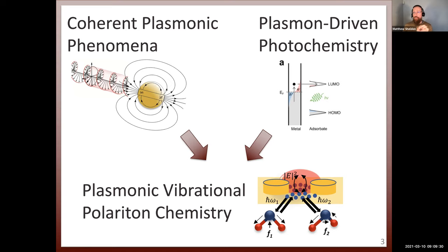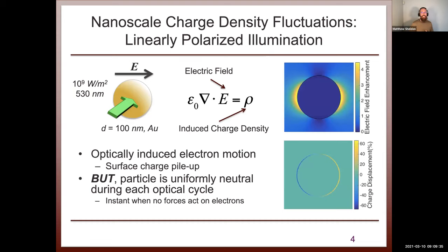If you've ever seen someone talk about plasmons or plasmonic systems before, you've probably seen some kind of diagram or depiction like I have on this slide. The remarkable thing about a plasmonic resonance, in a small nanoscale subwavelength piece of metal, is that the electrons are responding coherently to the driving optical field. This causes a mechanical feedback resonance, in the limit of a subwavelength structure, that can greatly enhance and concentrate the optical field in the subwavelength near field around the metal.